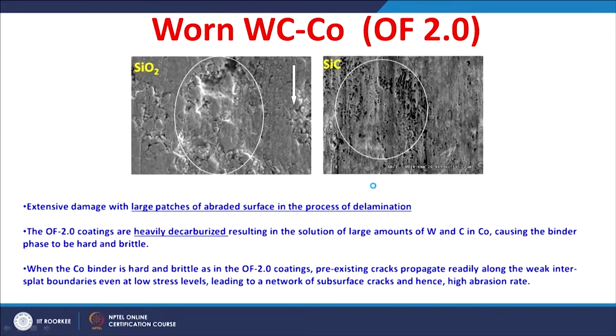These are the worn surfaces of the tungsten carbide cobalt coating with an oxygen to fuel ratio of 2.0. You can see the extensive material removal with large patches of this material abraded and then delaminated. The oxygen to fuel ratio of 2.0 coatings are heavily decarburized. As I told previously, the decarburization is of the order of around 45%. Because of the heavy decarburization, that results in the solution of large amounts of tungsten and carbon in the binder phase.